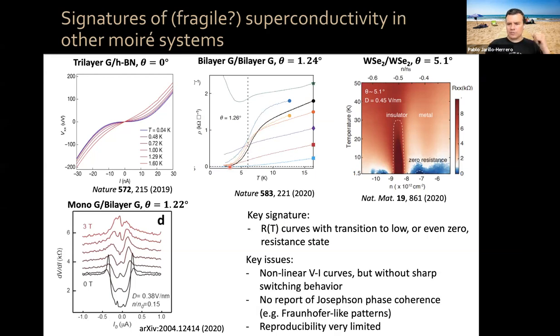However, there are key issues that make people doubtful whether these are truly superconductivity, or maybe this is very fragile superconducting behavior. One is, for example, that the nonlinear voltage-current characteristics, although they are nonlinear, do not have sharp switching behavior. They're more nonlinear like this, and this is not necessarily superconductivity. And most importantly, there's no report of Josephson phase coherence from Fraunhofer-like patterns in any of these systems. And the reproducibility in general has been very limited.